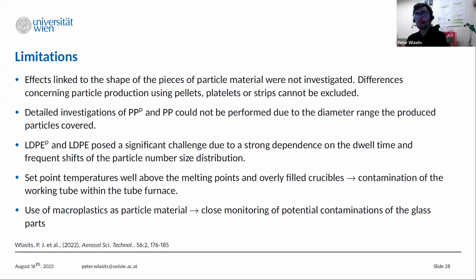Furthermore, we couldn't do detailed investigations of higher purity and commodity polypropylene due to the diameter range of the produced particles, as you've seen. Higher purity LDPE and commodity LDPE posed a significant challenge due to a pretty strong dependence on the dwell time, and that also yielded frequent shifts of the particle number size distribution. So it was not really that reproducible, to be honest.